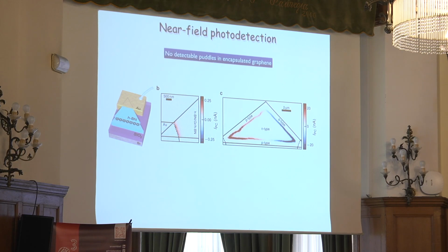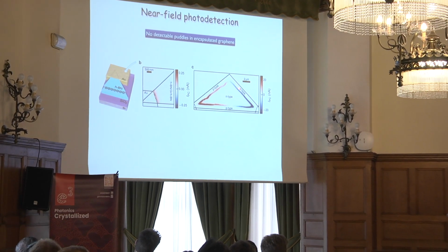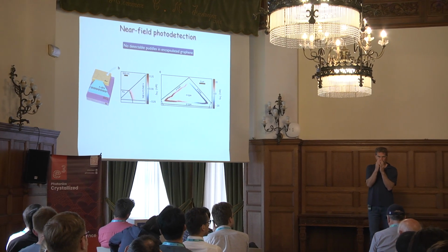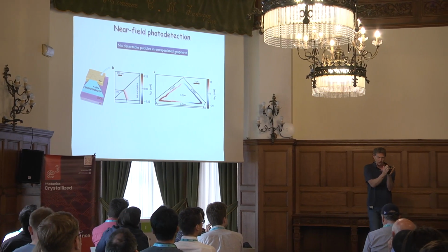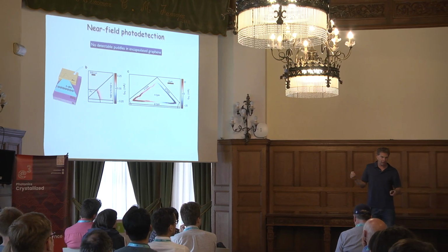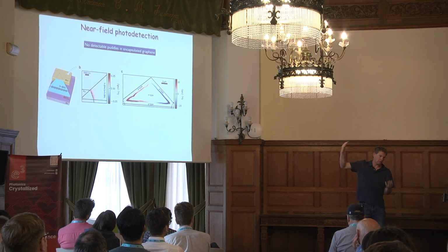Yeah, I see the currents are really large compared to the CVD. It's like 100 times higher. Is this for the same voltage that you apply? Yeah, they're much larger. It is because this is a very well-defined junction. I will show later, but basically we're probing the gradient of the Seebeck coefficient. And if there's a very sharp jump in Seebeck, you get a larger photocurrent.